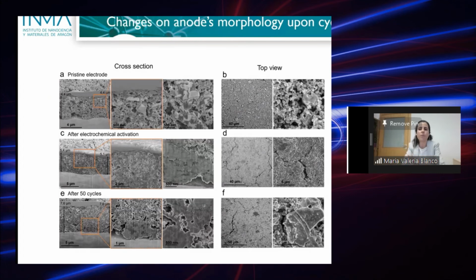Also, we did some inspections of the cross-section of the electrodes to see how the morphology of the anodes evolves upon cycling. So what you can see in the left part of the figure is the cross-section of the pristine electrode, then the electrode after the electrochemical activation, and then the electrode after 50 cycles of galvanostatic cycling. What you can see from the figure is that the thickness of the electrode increases with cycling, which means that we do have this expansion of silicon after all.